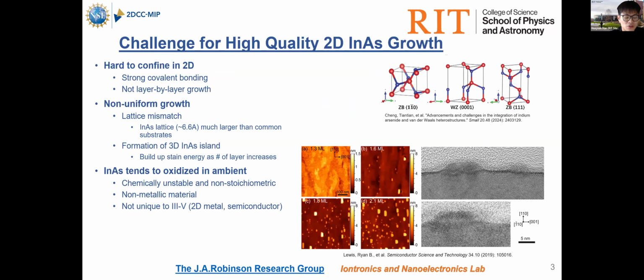However, the challenge for growing high quality 2D indium arsenide is, first of all, that this material has strong covalent bonding, so it's not intrinsically a layer-by-layer material. Confining it to completely lateral growth is a challenge. Second, it usually has a non-uniform growth property because indium arsenide has a lattice of about 6.6 angstrom, which is much larger than common substrates such as silicon and sapphire. Therefore, as you grow the material, such lattice mismatch will induce higher energy as the layer number increases.